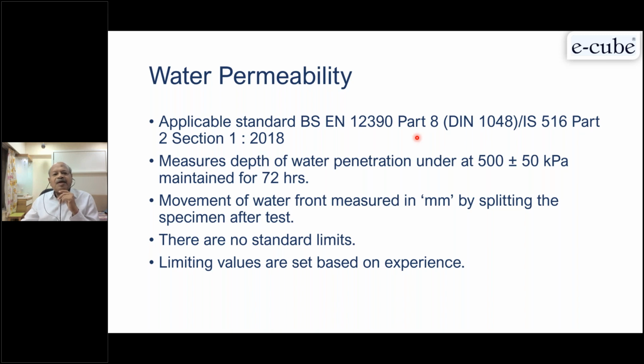What we have to do is apply a water pressure of 5 bar for 72 hours, and water moves into the concrete. You split the specimen, and then we can see the depth of water penetration. Then you design various binder contents and so on, and go with the minimum specified for the project. There are no specific standard limits given. Generally, for normal work, we accept around 25 mm. Railways earlier used to do this test for their bridges, and their limit was 25 mm. But slowly, for normal work, around 15 to 20 mm is also very good concrete.